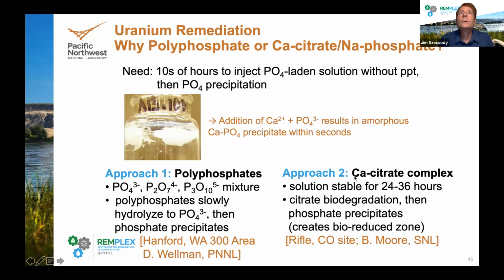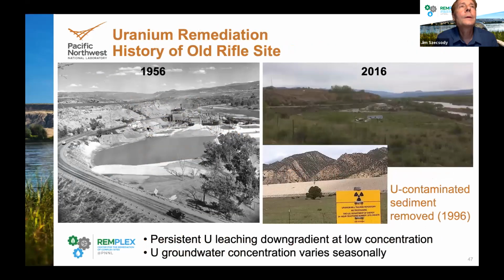Another way is to complex the calcium. A calcium citrate, sodium phosphate solution can be injected without precipitation, and then the citrate is biodegraded in the system, and phosphates are formed. The polyphosphate approach, which was used at Hanford, was developed by Don Wellman at PNNL, and the calcium citrate phosphate method was developed by Bob Moore at Sandia National Labs. That was also used at the Rifle site, which is what I'm going to talk about next.